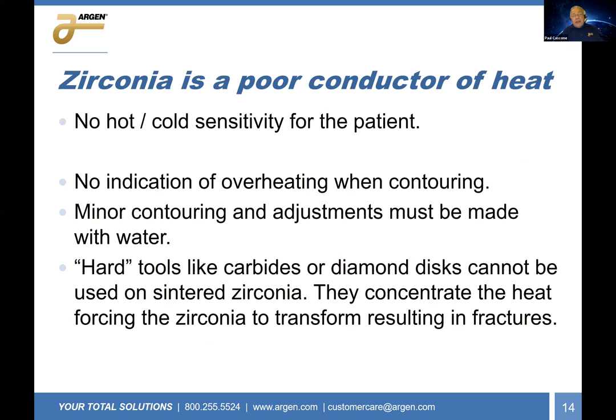Now also zirconia is a poor conductor of heat. So that's great for the patient because you're not going to have any hot or cold sensitivity. But on the other hand, there's no indication of when the material is being overheated. So it's not going to get warm in your hands. It's just going to crack. Any minor contouring or adjustments on sintered zirconia must be made with water, copious amounts of water. And the word copious, I can't underestimate. You're hitting it with a high-speed carbide.